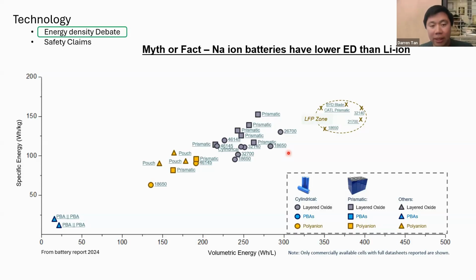Both are true. I would say I would agree. So sodium really only kicked off commercially, I'd say, in the last 4 years or so, whereas lithium has had 30, 40 years of work done. And it is improving at a rapid rate. So sodium got from probably this region to here in the last 4 years. It won't be surprising if sodium is here in the next 4 years. But that also assumes that lithium doesn't continuously improve. And we see a lot of innovations in LMFP, manganese-doped lithium iron phosphate. It could be an interesting study to look back at the rate of improvement per year of lithium. Anyway, that's a side topic. But that was just a good insight.